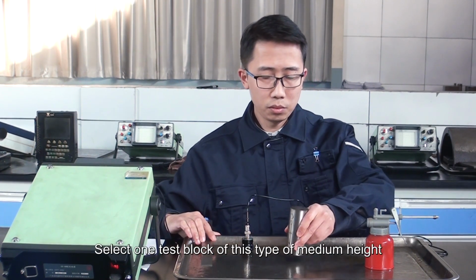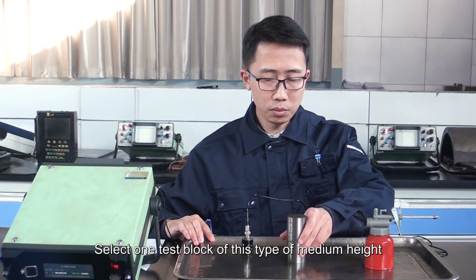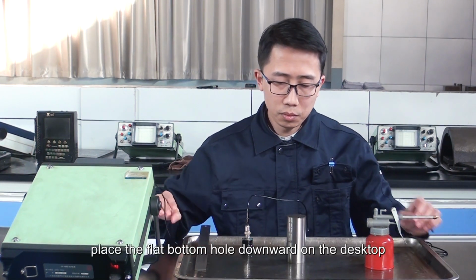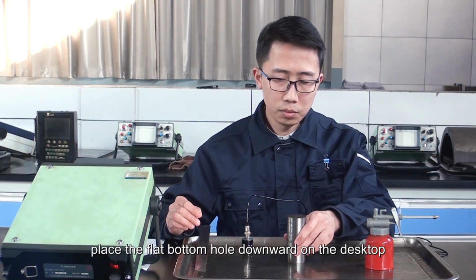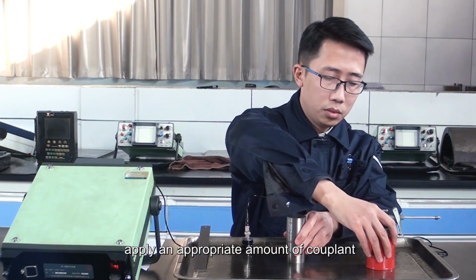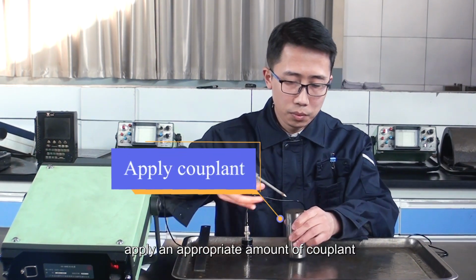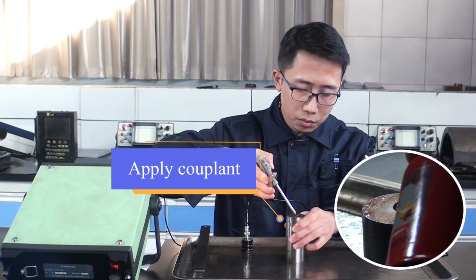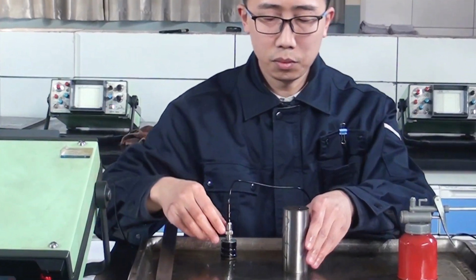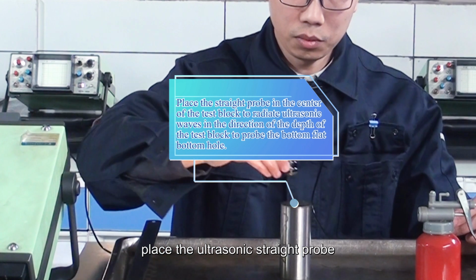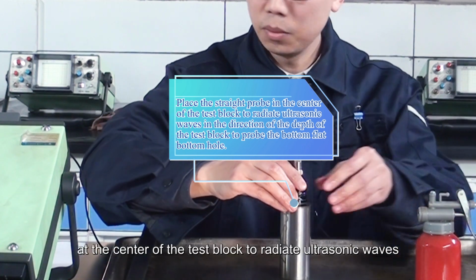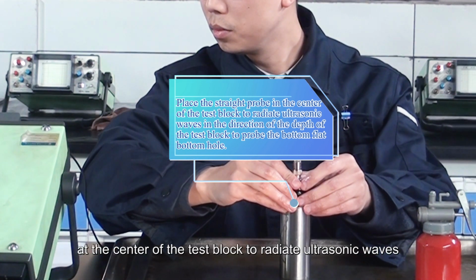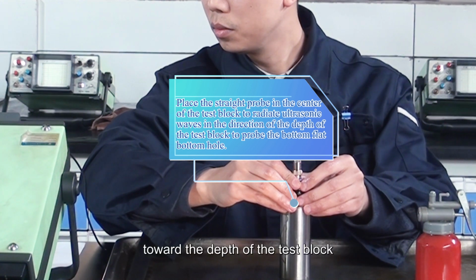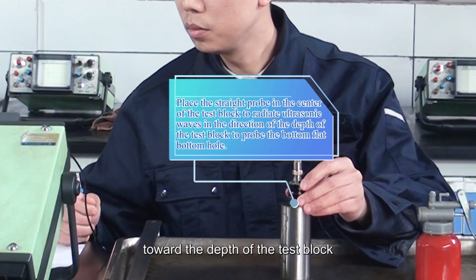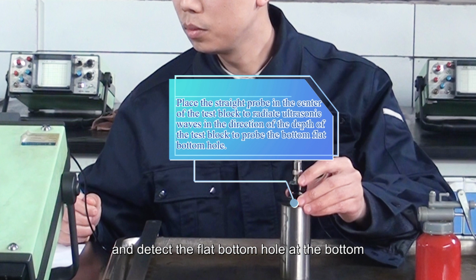Select one test block of this type of medium height. Place the flat bottom hole downward on the desktop. Apply an appropriate amount of couplant on the testing surface. Place the ultrasonic straight probe at the center of the test block to radiate ultrasonic wave toward the depth of the test block and detect the flat bottom hole at the bottom.